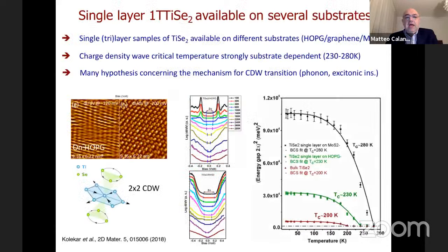The first one I would like to consider is the single trilayer of 1T titanium diselenide, which, by the language I just told you, means that titanium is in octahedral coordination. The system is very interesting in single layer because, first of all, for a long time it was very difficult to obtain. It is a metallic dichalcogenide, and all the dichalcogenides we will consider now are metallic, or semi-metallic, because these are the ones that display charge density wave instability. The insulating ones do not.